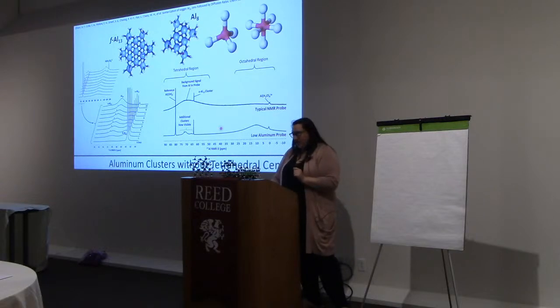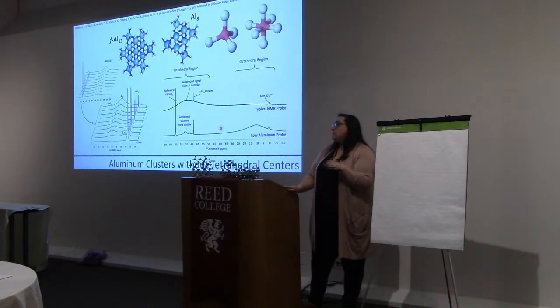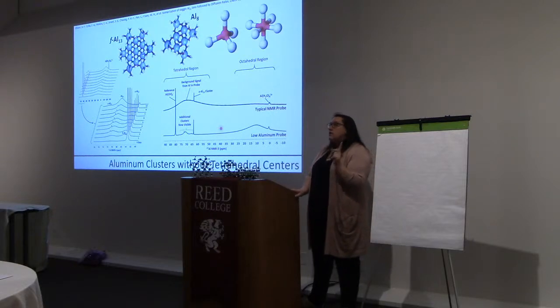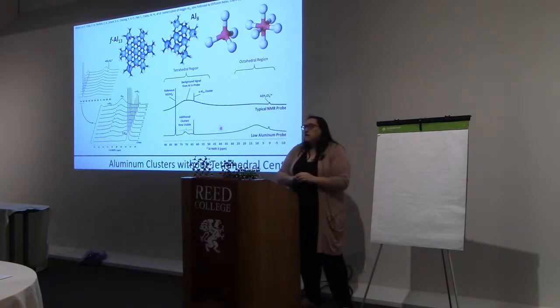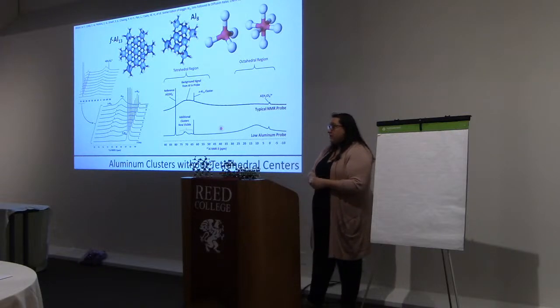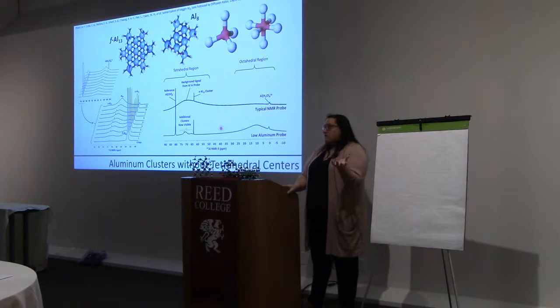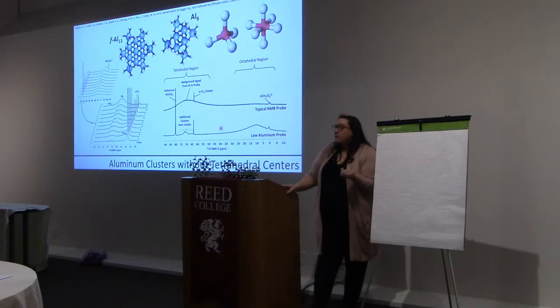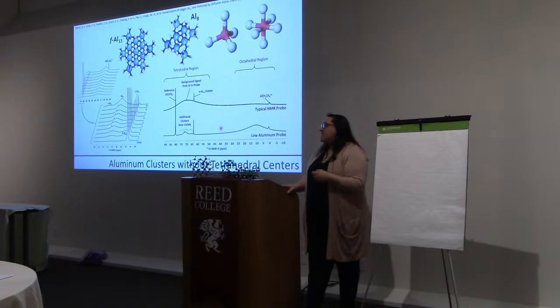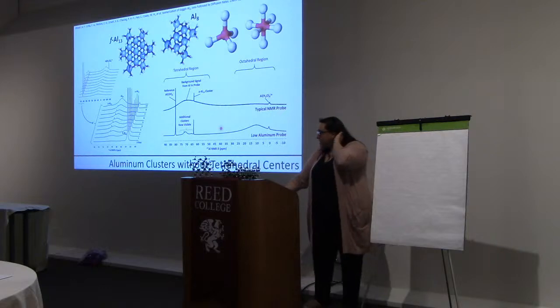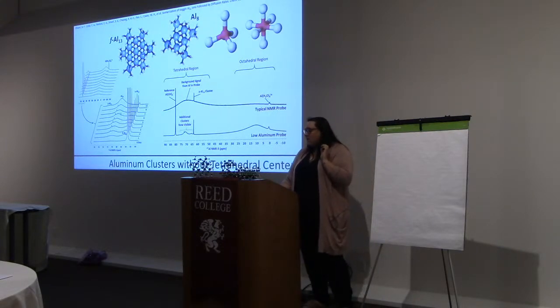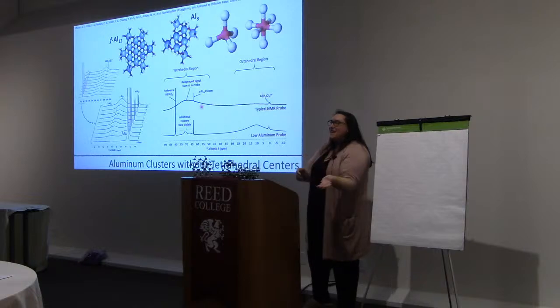Now, unfortunately, we can't do that at SOU. Our NMR is old, but there is also another reason we can't do it at SOU. At UC Davis, I worked for a geologist. He was in the chemistry program, so we were looking at this from a mineral standpoint, and he had purchased a very special NMR probe that did not have aluminum in it. Aluminum's non-magnetic, it's really light, it's cheap, so most NMR probes have it in there. And so we get this huge background signal covering up all this beautiful data that I was showing you where we can see all those isomers. So at SOU, we can do aluminum NMR, but I can't see any of the beautiful data that I want to see.